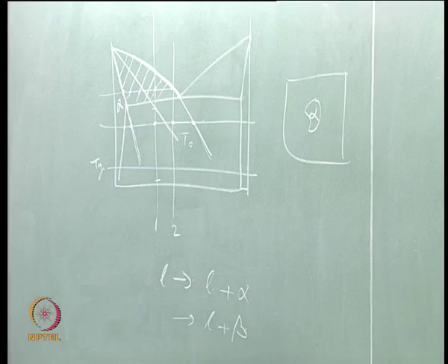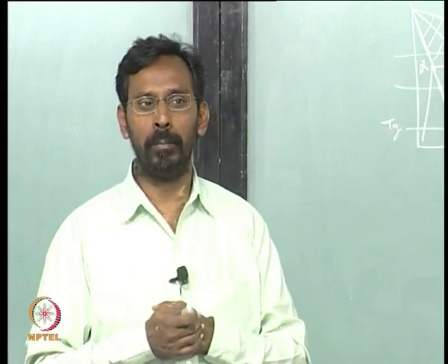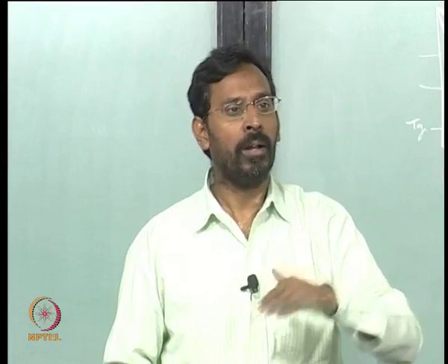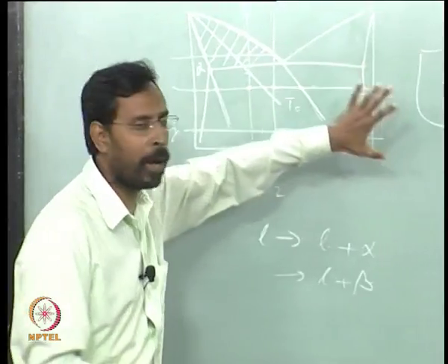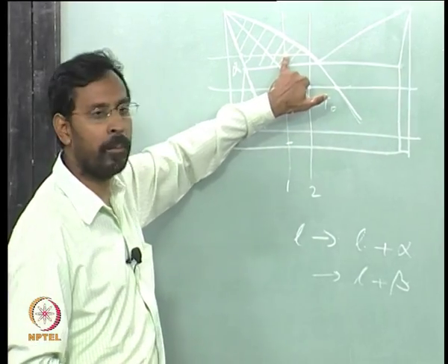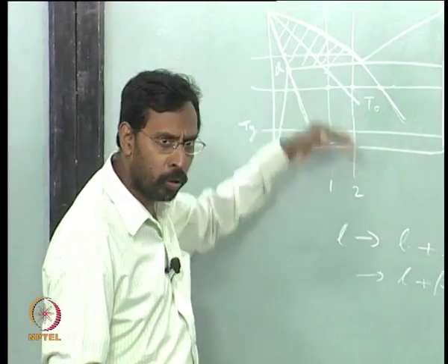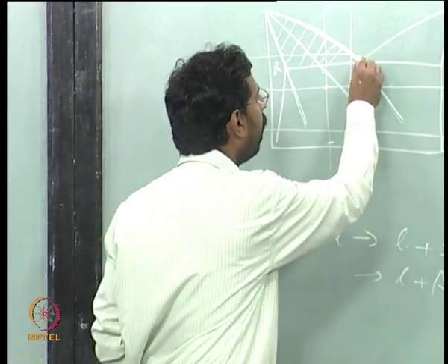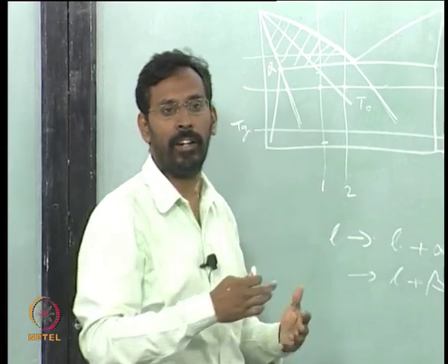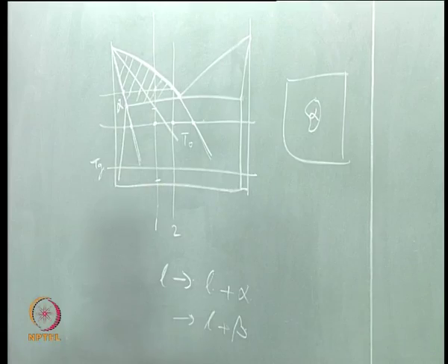If partitionless solidification is not taking place and you are at a temperature below the eutectic, there is a problem. If you are above the eutectic, all this problem does not happen. Here at this temperature you will hit alpha, and as you cool to lower and lower, the liquid composition changes, and then finally it reaches eutectic, and that liquid will give you a eutectic mixture like any other solidification.